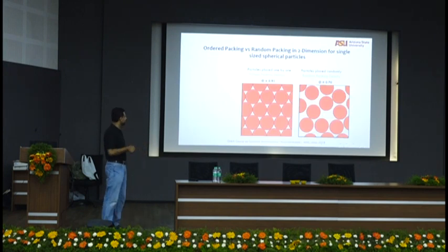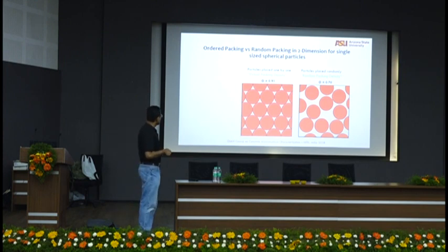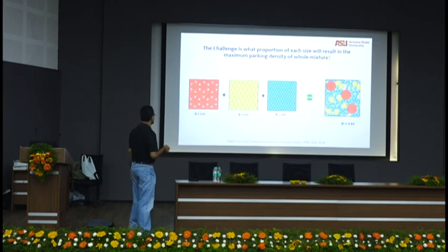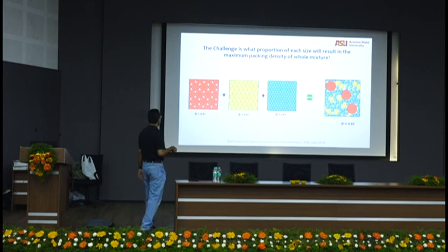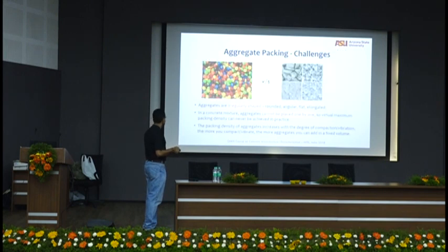So you have, again, I showed this in the morning. If you pack particles one by one and change the sizes, again I have shown only one size, but you can have multiple sizes. Even then, your maximum packing fraction is 91%. Randomly, if you start putting in a microstructure, what you can get is 70%, but that's not enough for us, right? 70% is not. So you have to go to a higher value. If you use multiple sizes, then you can go all the way up to 0.84, which is actually good.